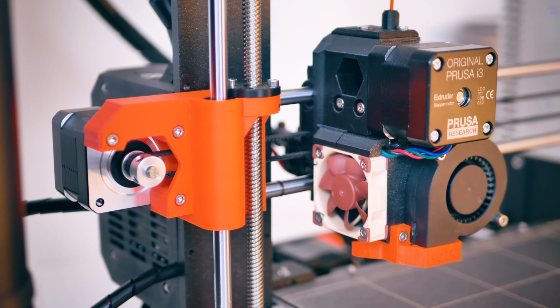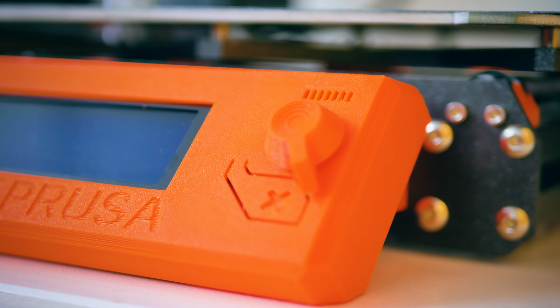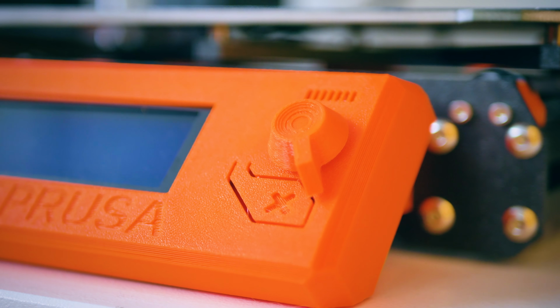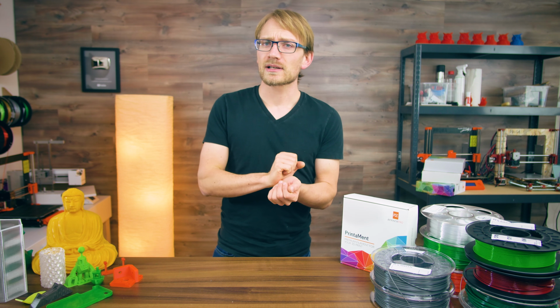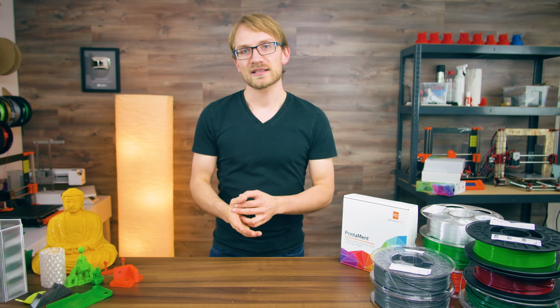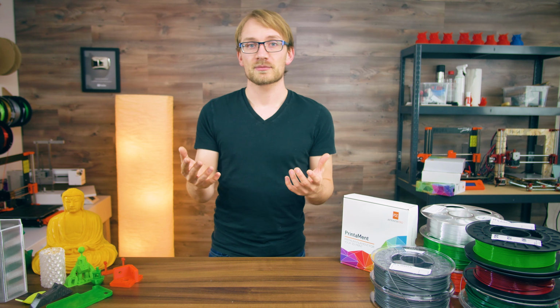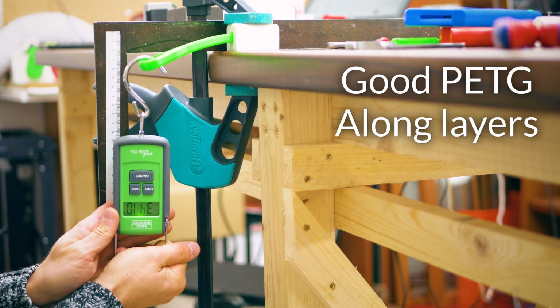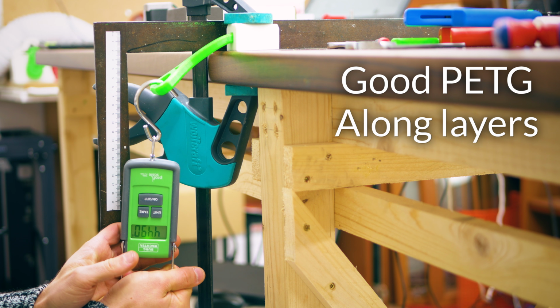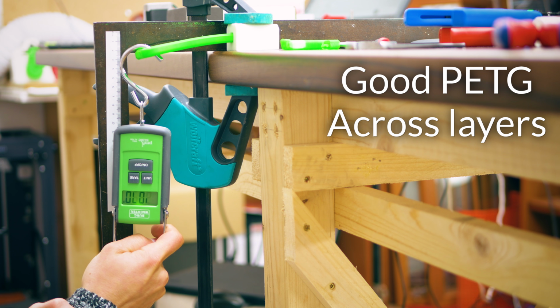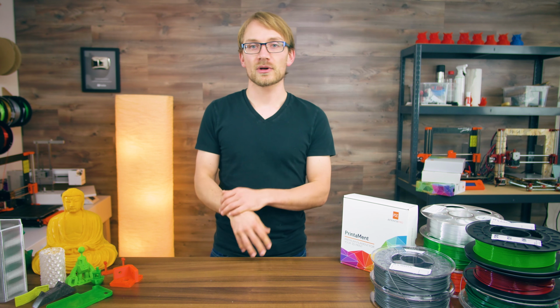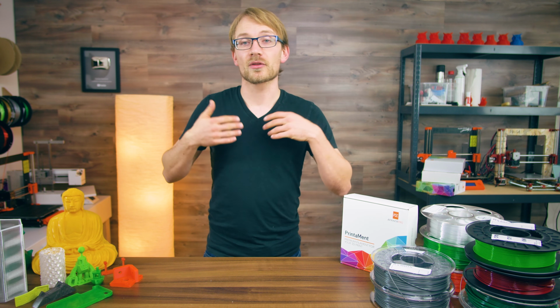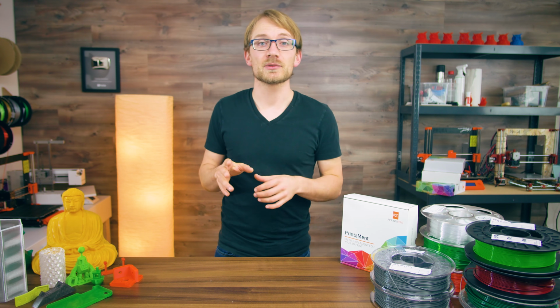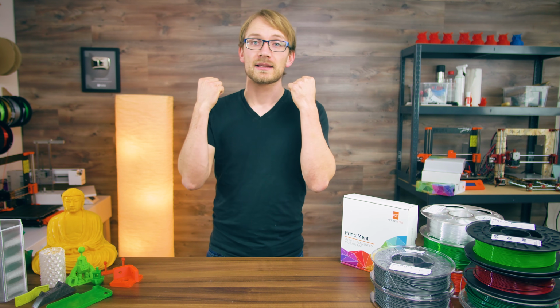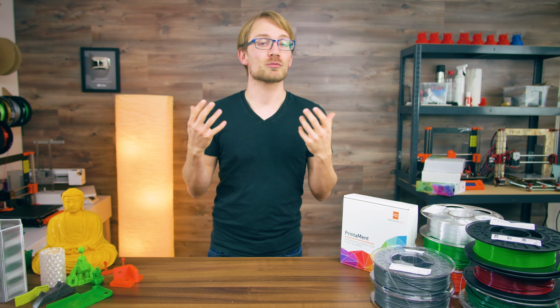PETGs are also really strong and came out with consistently impressive results in the Halloween tests, but their strength, even though it is good, feels a bit less predictable than other materials, because some copolyester prints like to shatter instead of gradually failing. What can make this behavior much worse is when you use wet PETG. Through a process called hydrolysis, the water steaming up as the plastic gets heated will essentially tear apart the polymer chains and make the plastic more brittle.